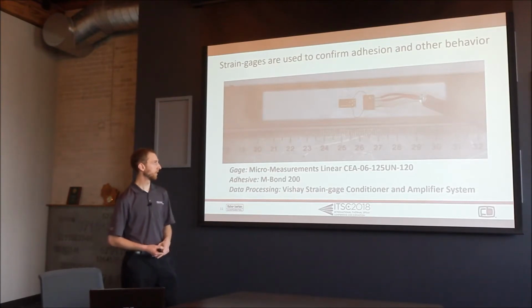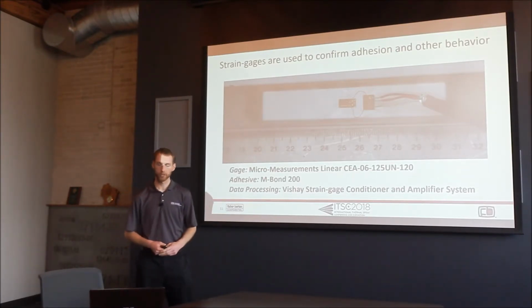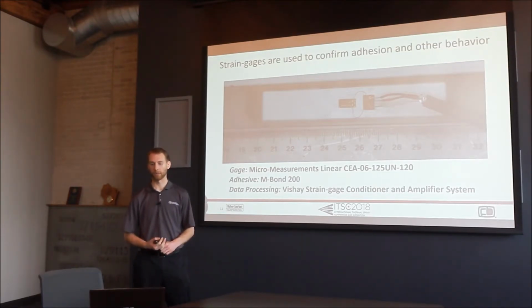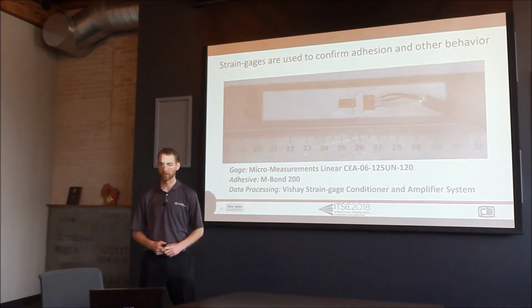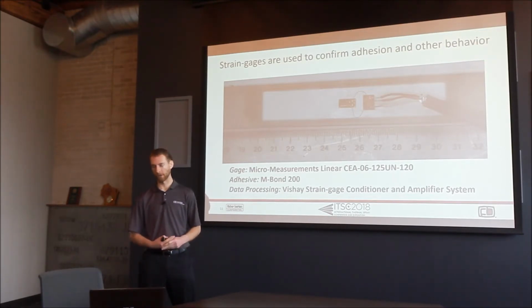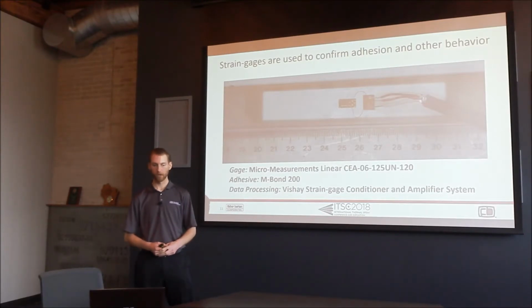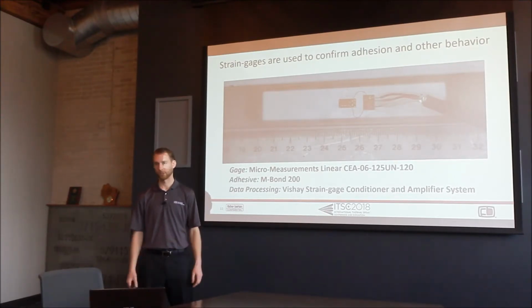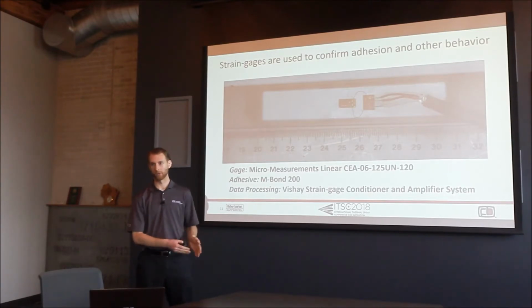In order to detect whether we have adhesion or not, we're applying linear strain gauges to the top surface of the coating. You can see the coating is not applied across the full width of the sample, as we wanted to reduce any edge effects, and our strain gauge is in the middle of that coating patch. We're using strain gauges for micro measurements. It's a linear strain gauge whose thermal expansion matches the substrate in this case. So the gauge selection does play a role, depending on what substrate you're using and what temperatures you're running. It's applied with Micro-Measurements M-Bond 200, and then we're using a strain gauge conditioner and amplifier system to process the data and convert voltage to strain.